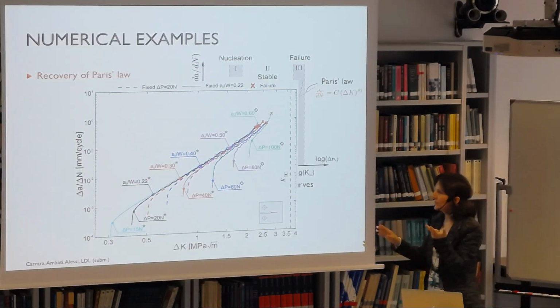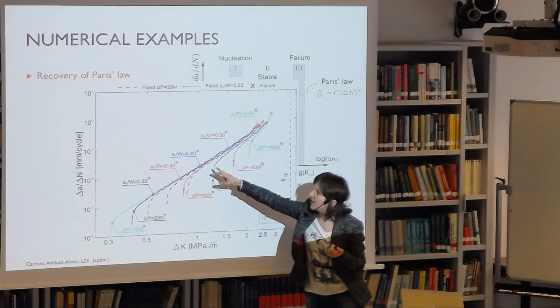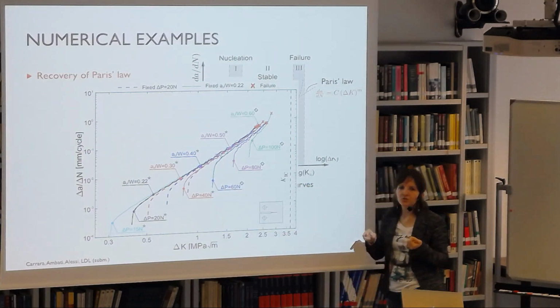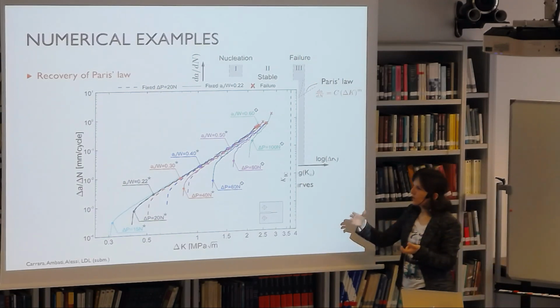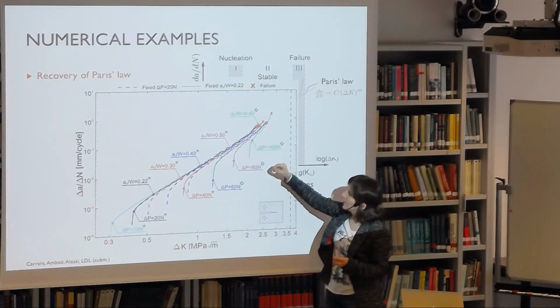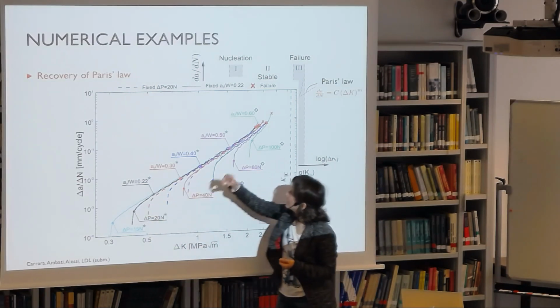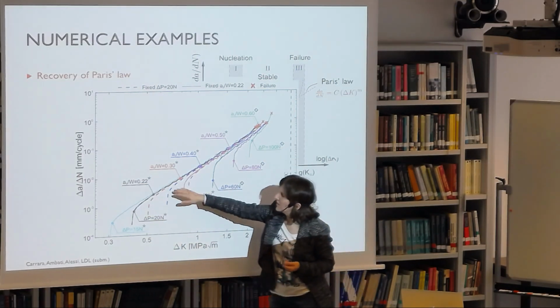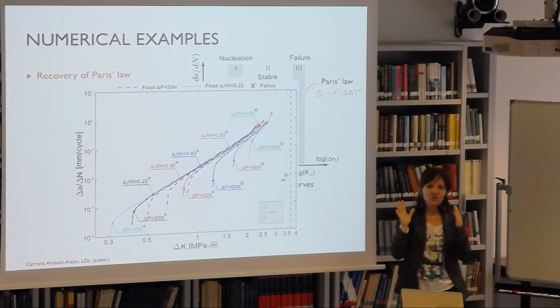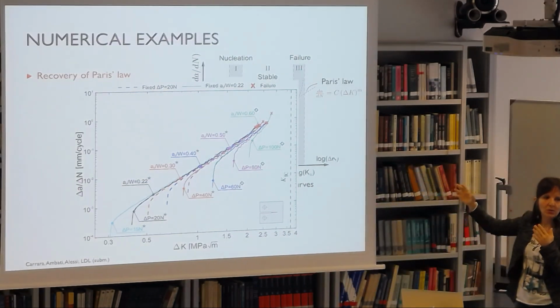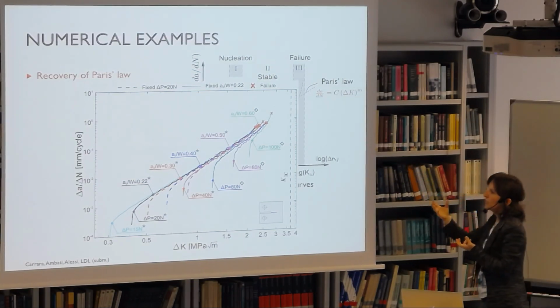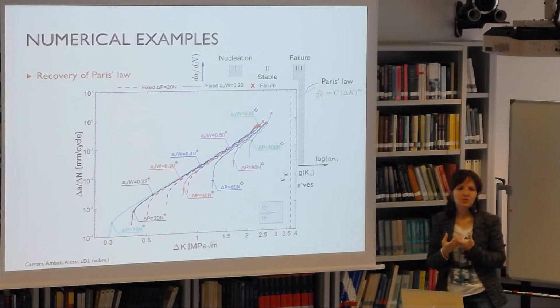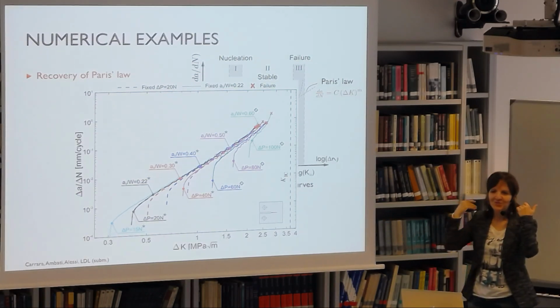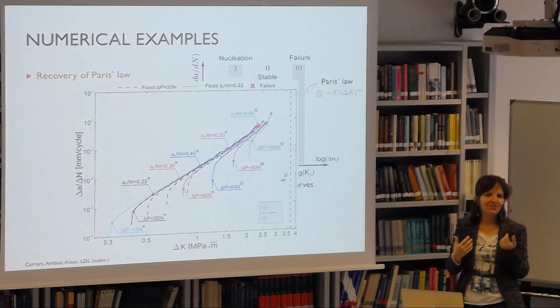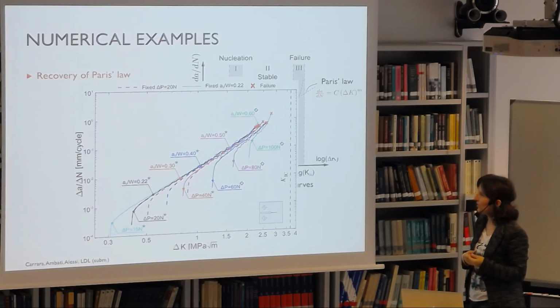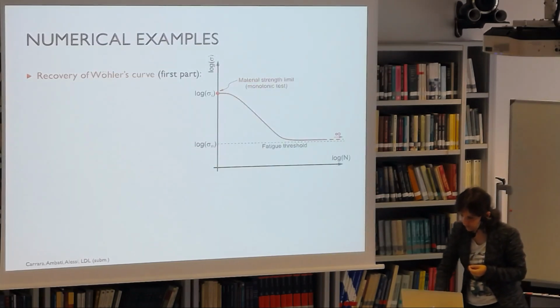In this case the geometry is fixed, but we change the initial crack length and we change the applied load to recover the same delta K, and we found out that all the possible choices that we made led to different initiation branches and different failure phase branches, but the middle range is given by a fairly linear law where we can basically identify C and m based on numerical results instead of experiments. Of course, assuming that we have first identified our fatigue degradation function, which is basically what we need to identify through the comparison. So we were pretty happy about this.